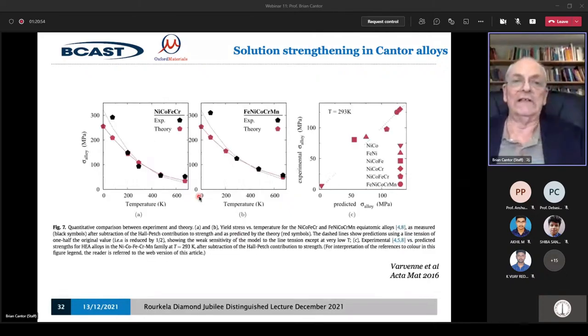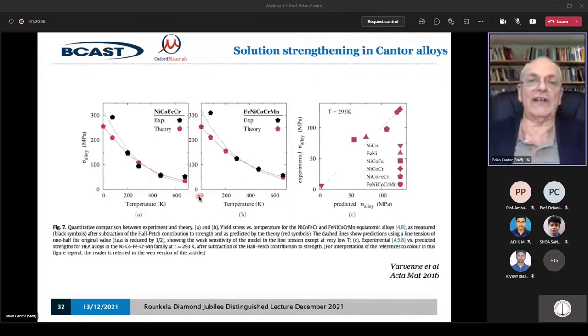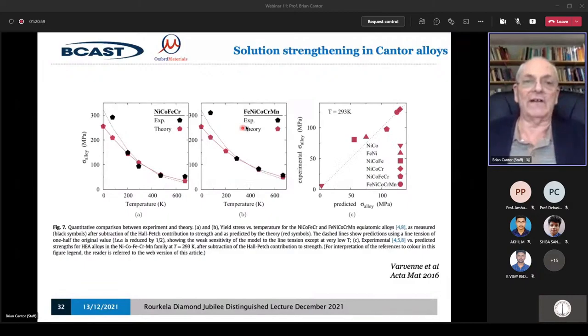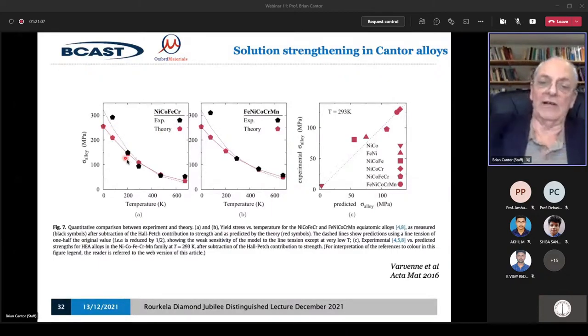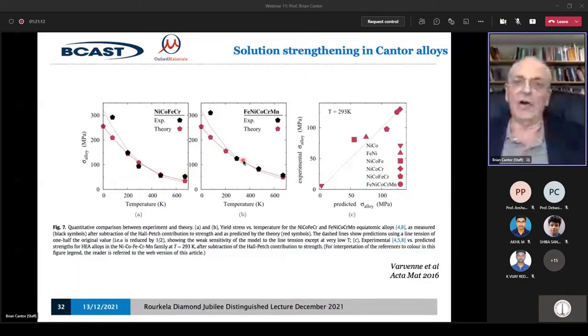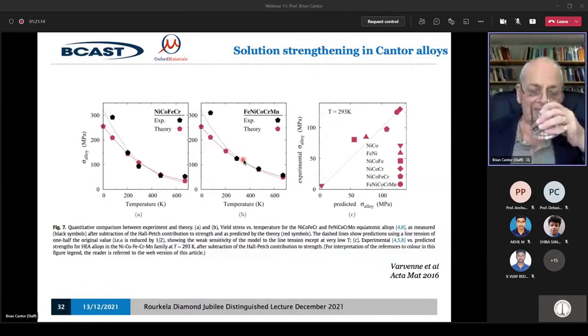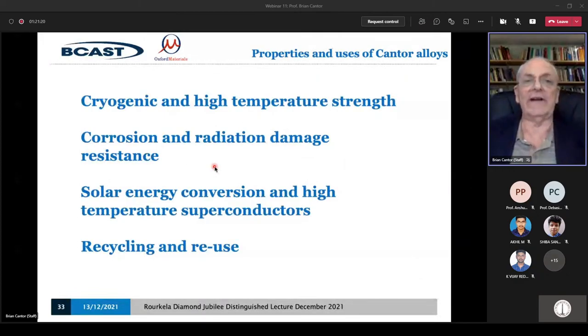Here's the Cantor alloy itself. Here's, again, a modified composition Cantor alloy. The black things are the experiment and the red things are the theory. And they give fantastic agreement between experiment and theory. And this has now been done in quite a lot of different cases. So this is a good example of what's going on. So what are the properties and uses of high entropy multi-component alloys, and in particular Cantor alloys? Well, the Cantor alloys have already been shown to have the best cryogenic properties, low temperature properties, of any material known at low temperatures. So they're being looked at to be used at low temperatures.